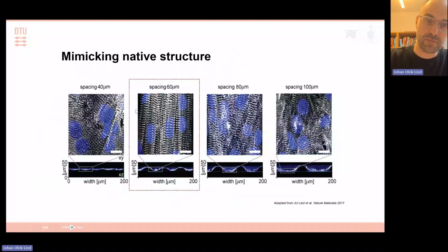you can see, hopefully you can appreciate from this picture, that along these grooves we get an anisotropic organization. If not, it's more clear here probably that you can see all the sarcomeres. That's the contractile units of the cardiomyocytes. They all pull in the same direction. And that is obviously very dependent on the geometry that you print. If you have no features here, then you get very isotropic tissue, and there's a trade-off between the spacing and the feature size that you can play with in your printing.